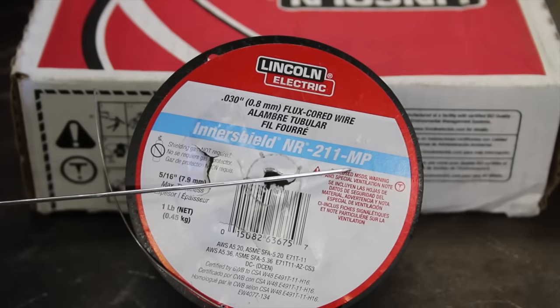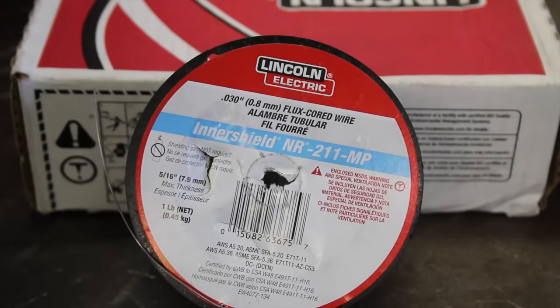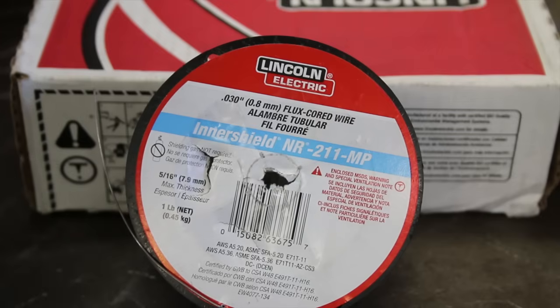The MP is very important, that stands for multi-pass. If you do not have this MP on your particular flux core, or if your flux core says SP, which is single pass, then that means you cannot weld more than one pass with that particular wire. So if you stack another bead on top of it, you will have problems. It will fail eventually. So make sure if you're going to weld bead after bead that it says MP for multi-pass.